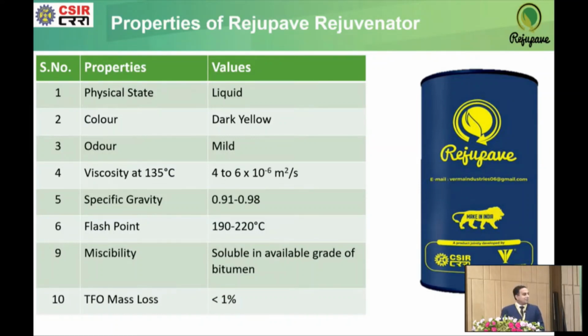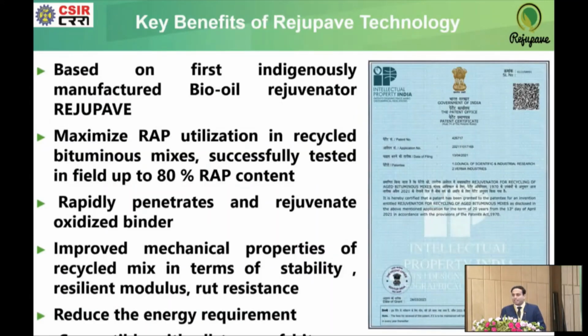In one of the NH-53 sections, the National Highway section in Surat, I am utilizing 50% reclaimed asphalt pavement material along with processed steel slag aggregate. Parallelly, whatever distressed material has been recovered, we are reutilizing it with processed steel slag aggregate. So there is no natural virgin aggregate inside it. The balance quantity of the bitumen, like 1 to 2%, can be added with the help of virgin VG40 or VG30 grade binder. In this regard, we have received the patent; it is India's first bio-oil based rejuvenator.